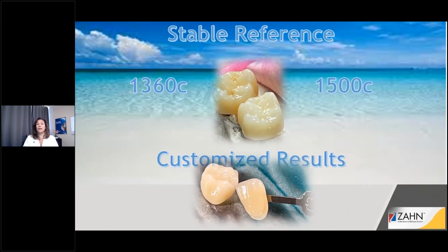So what you want to do next is decide what is the perfect sintering temperature for you. Another great thing about the Transitions is that you have a range of sintering temperatures that are acceptable, and they are within the range in the IFU. There's a new IFU coming out. I think a new IFU has already come out, and I was really surprised to see the low temperature that you can sinter at. So 1360 is the actual low temperature that I ended up sintering on, and I liked the most.